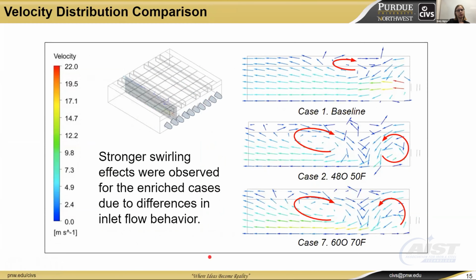This shows a comparison between fluid flow behavior along a vertical plane intersecting one of the burners for the baseline and the two optimal enrichment cases. One of the main things to note here is that higher turbulent effects occur for the enriched cases due to the high velocity with which oxygen is injected. And this is positive in the sense that it promotes mixing for the enriched cases because a lot of the oxygen is injected further away from the fuel than it would be for just the air-fired burners. This allows the fuel and oxygen to mix in a way that is then comparable to the baseline case.